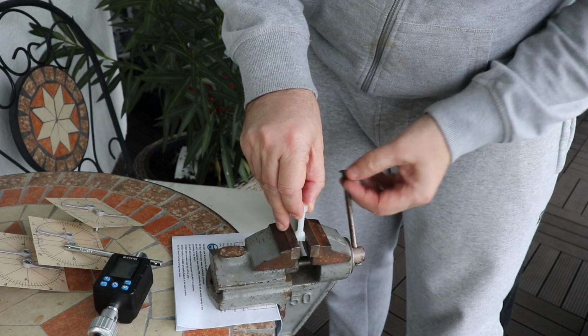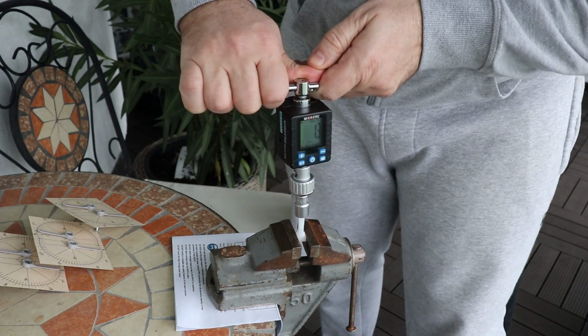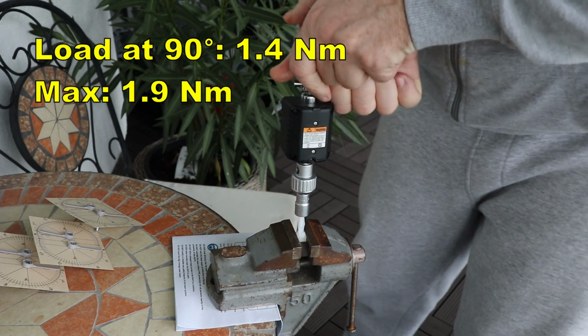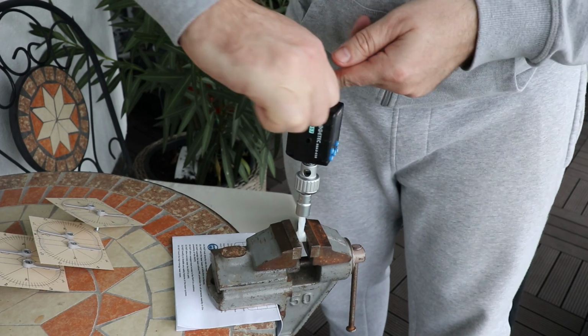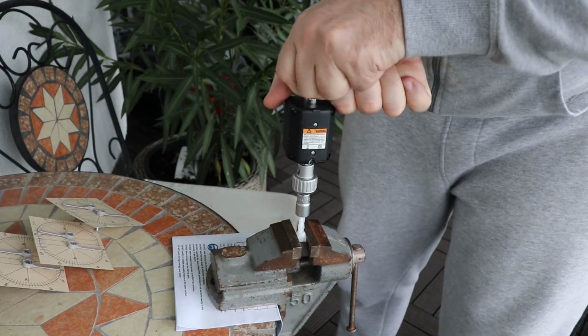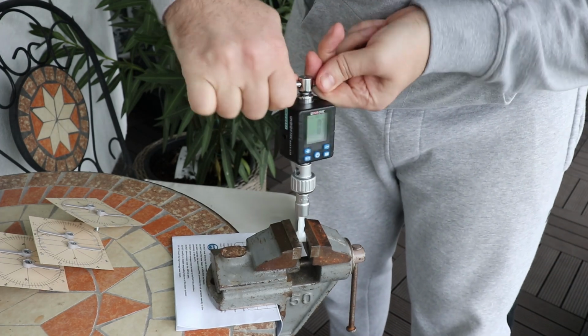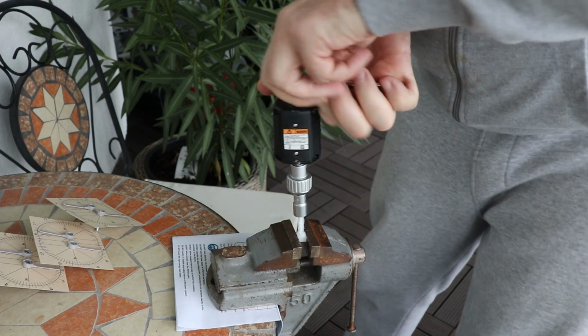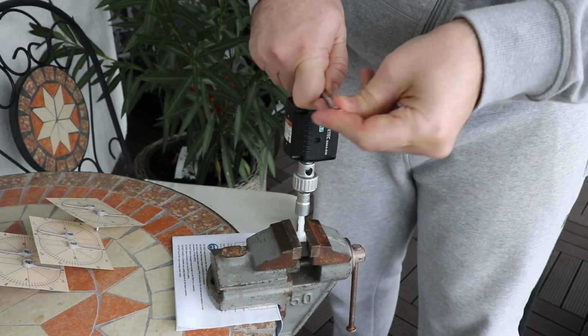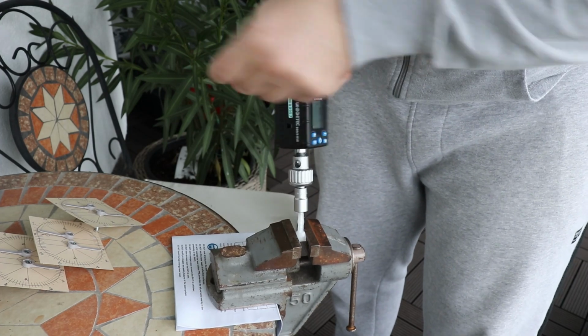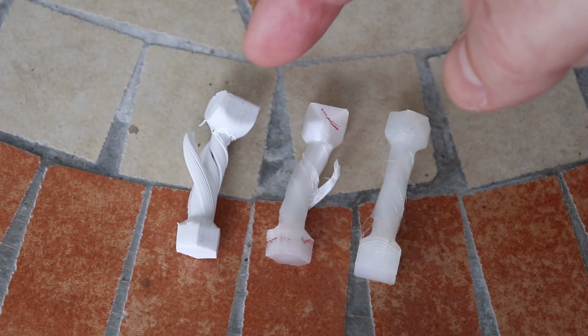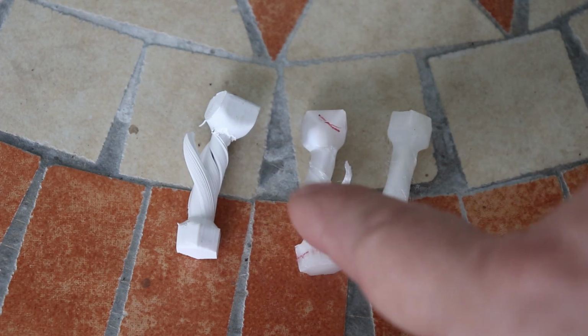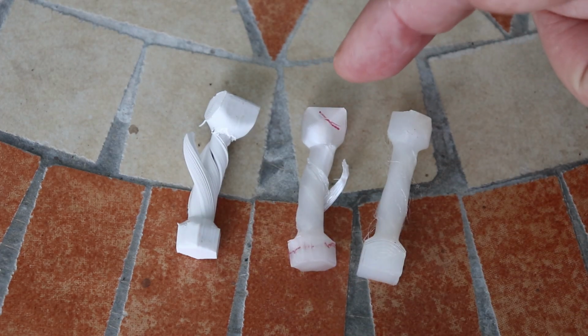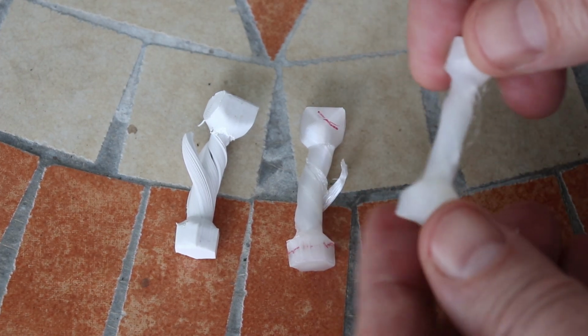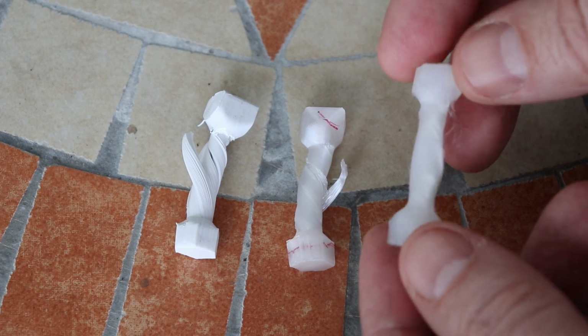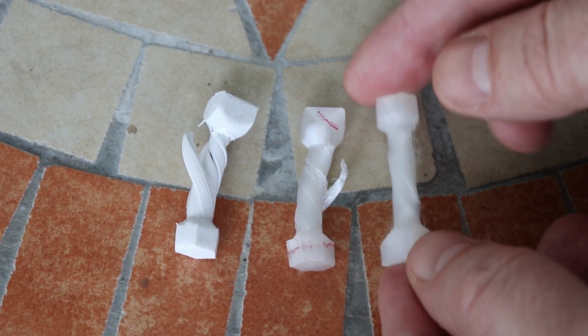And the nylon. 0.9 is the peak so far, and it doesn't really break yet, it's more like elastic. ABS broke quite quickly. Similar was the polycarbonate, and as you can see, this is a sign of the weaker layer adhesion, and that's what we saw in that experiment. And nylon, it didn't actually break, and here I could make maybe almost 2 twists until I feel it's deformed, but it didn't break at all.